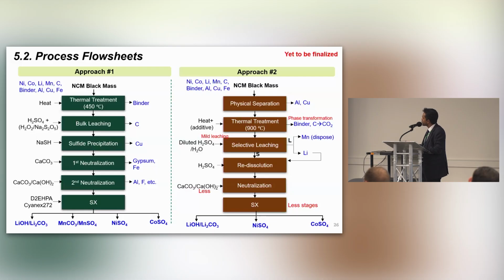And in approach two, we are targeting NMC black mass for selective leaching. In this case, we try to separate out the aluminum and copper, so that we could reduce some chemical costs downstream that are used for this kind of impurity removal. And by applying different types of thermal treatment and selective leaching, we separate out graphite and also binders. Especially in the case of manganese, some industries consider manganese not that economical to produce for battery material. So if we consider it as a disposal item, then this process targets making lithium, nickel, and cobalt only, but reducing the chemical cost and the number of operation stages.